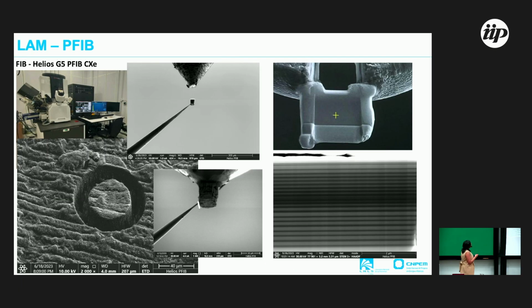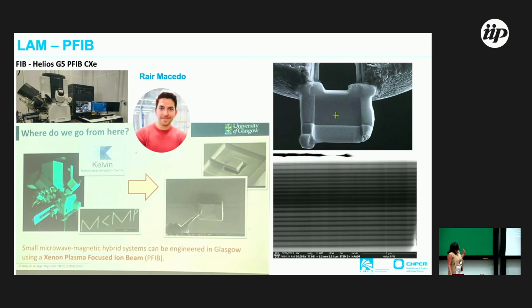Additionally, we have the microscope, the dual beam, that allows us to produce many different building blocks. As you can see, we use here the xenon ion beam to remove some part of samples, and we can nano-manipulate the samples and put them everywhere. The same thing we can do for lamellas with well-defined and polished interface. We use that to prepare samples for beamline.